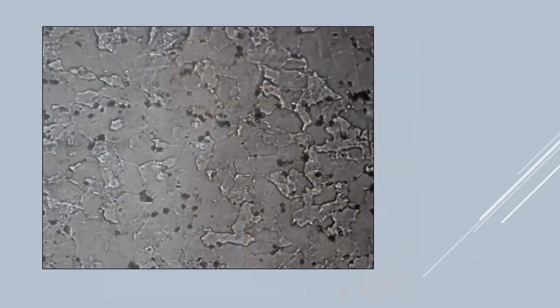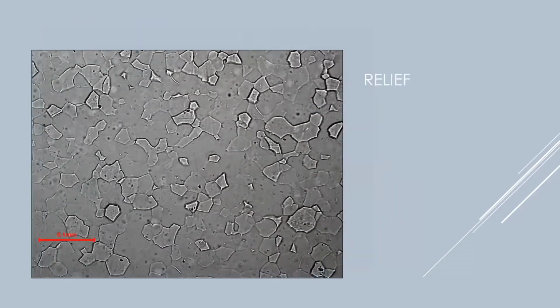So that paper with the fuzz is good for something like this, where you have lots of dust, but it's not good for other things, because otherwise what we get is relief. And relief doesn't mean the job is done, I go for a beer. Relief means I've got this three-dimensional effect here. You see these plateaus. This is a microstructure of just ferrite, and there's not a big depth of field on our microscopes. And so ideally we want something to be flat.